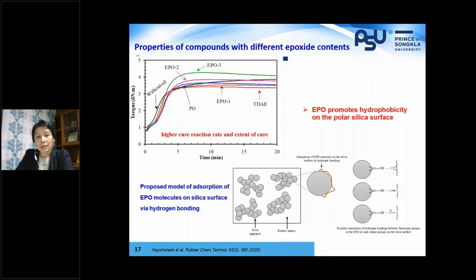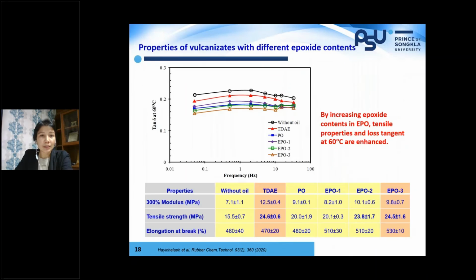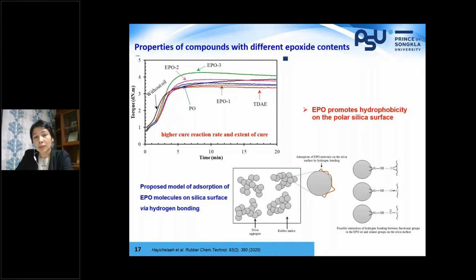I should mention that even if we have silane coupling agent with silica, and we do the silanization reaction during mixing, only about 25% of silanol groups can react with the silane coupling agent, because once some groups have reacted, there will be a steric effect, or steric hindrance, that prevents the incoming of new silane coupling agent molecules. So if 25% reacted, that means we still have plenty of silanol groups on the silica surface, and these silanol groups can still interfere with vulcanization.